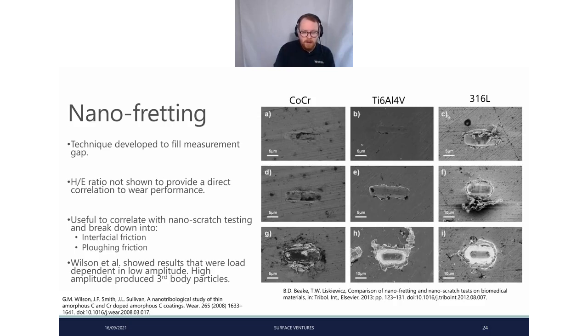So one of the things with this paper by Ben Beake is using multiple techniques. When we get to the nanoscale, it is extremely difficult, no one technique can control everything. It can monitor everything. So especially on this small scale, what you want to do is use as many techniques as possible that give you multiple pieces of information about your material, because this becomes more of a material characterization issue. With this we can look at wear depth, we can look at friction, we can then bring in nano scratch as well, to look at contributions of interfacial friction and plowing friction, because we're now looking at more fundamentals of interaction. And then with we're load dependent.